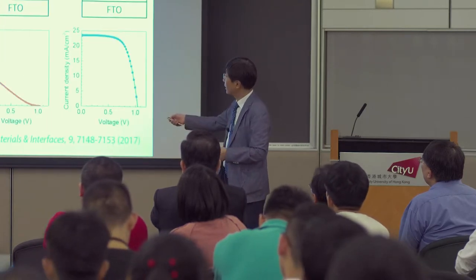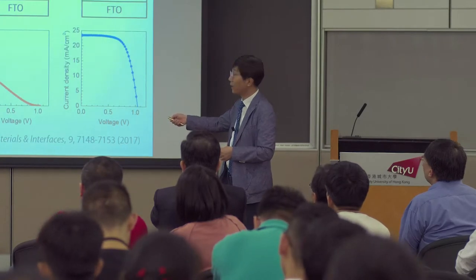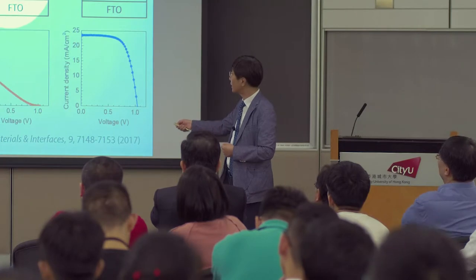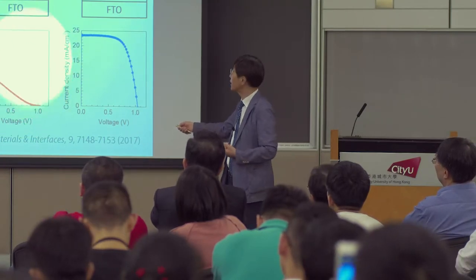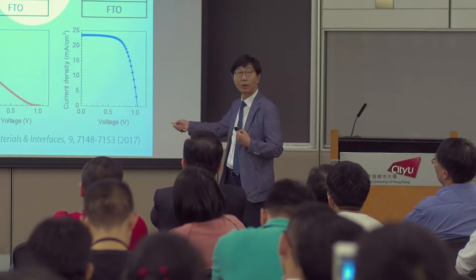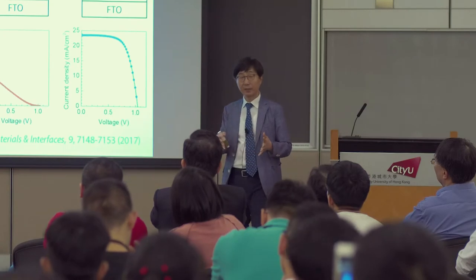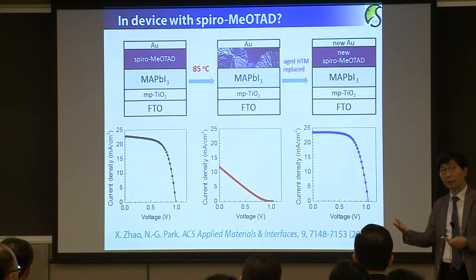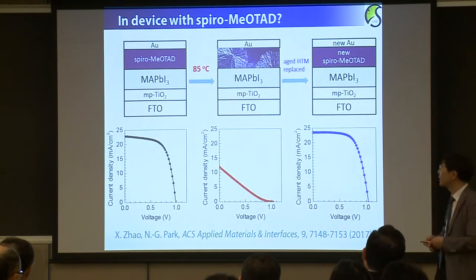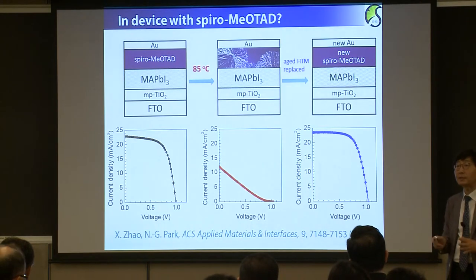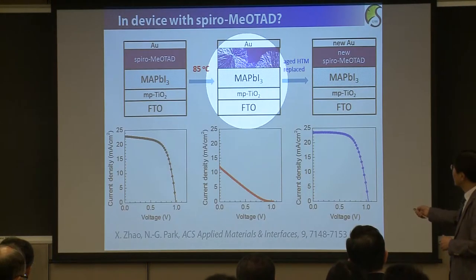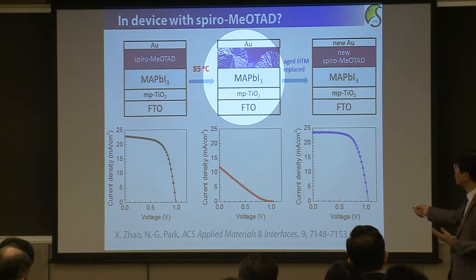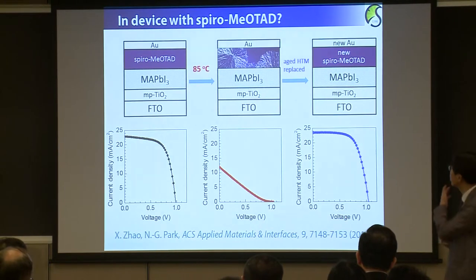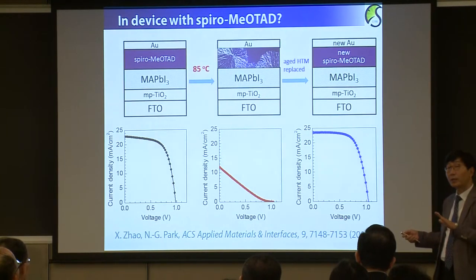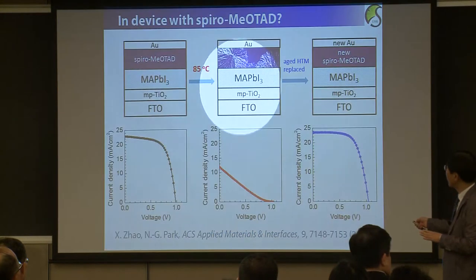But you see in the whole device structure, after the 85 degrees C thermal test, the solar cell actually died. But this is due to the spiro hole conducting material, because the spiro contains some additive, which further reduces the glass transition temperature. So 85 degrees is not a safe temperature. So probably after this temperature heat treatment, you lose some hole conductivity of this material. But we actually found that MAPbI3 is quite stable even after 120 degrees C.